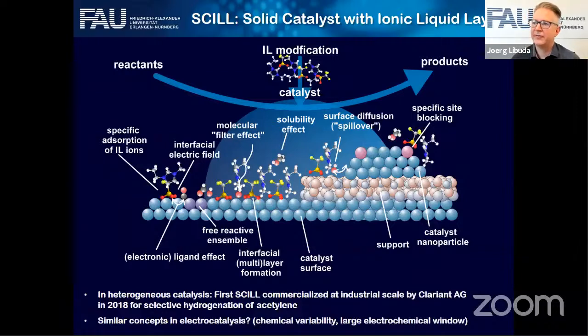And this is a concept that has been very successfully implemented in heterogeneous catalysis. There are actually commercial so-called SCILL catalysts, solid catalysts with ionic liquid layers around, which use this concept. Basically, people use a conventional supported catalyst, a noble metal on a support, coated with the ionic liquid, and then they hope that the ionic liquid would modify the reactivity of the system, and particularly the selectivity. It could do so, for instance, by blocking specific sites, by interacting with the reactants, by ligand effects, by electronic effects. You can think of all kinds of explanations why the ionic liquid could modify the reactivity.